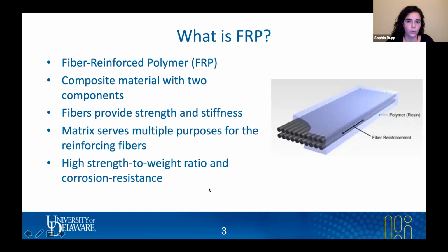For those of you who aren't familiar with what FRP is, it is a composite material that consists of two components. The first component is the fiber reinforcement, and then the second component is the polymer matrix, which surrounds the fiber reinforcement. The point of the fiber is to provide strength and stiffness for the composite material, and then the polymer matrix has a few different purposes for the composite. The first being that it provides an encasement for the fibers so that water can't get exposed to the fibers, making it corrosion resistant. It also ensures that the fibers stay aligned in one direction, making them unidirectional. And lastly, it ensures that the stresses in the fibers are transferred evenly throughout the composite material.